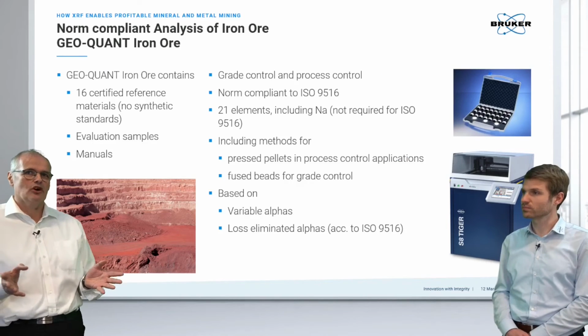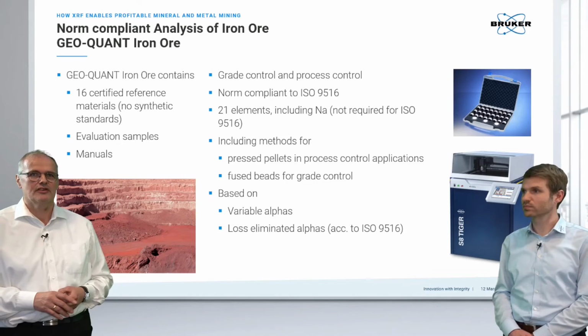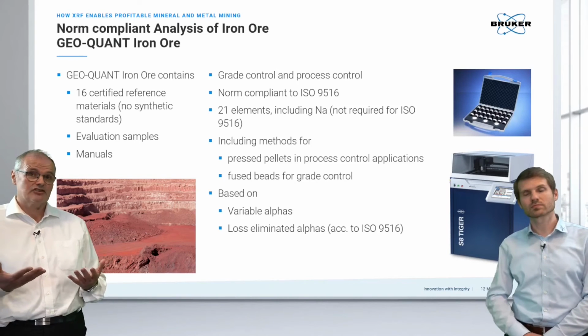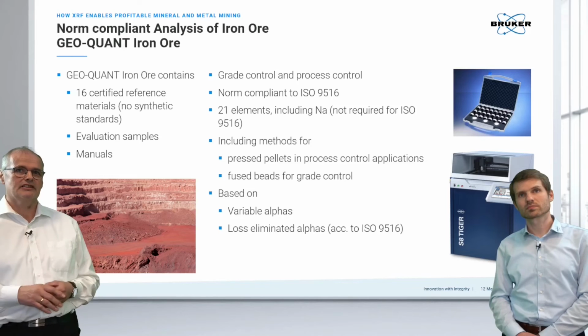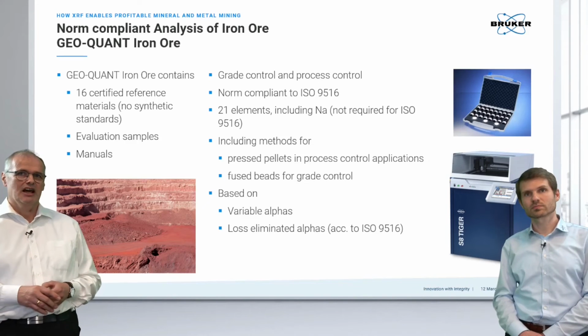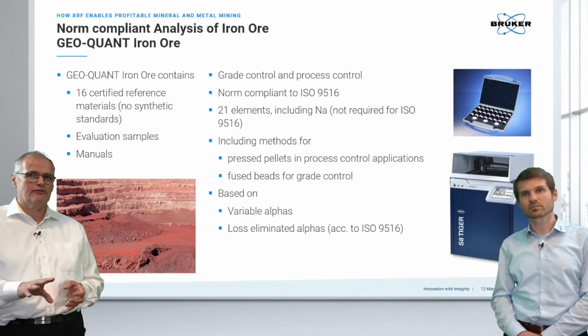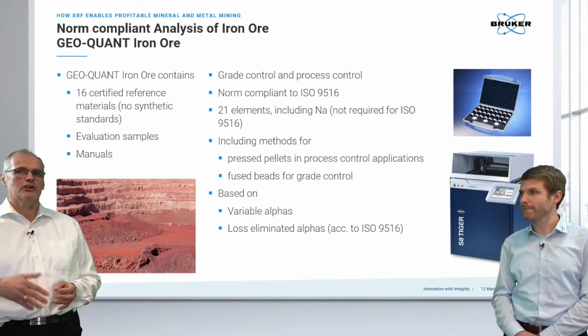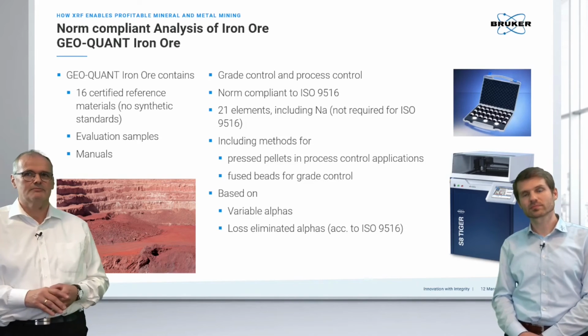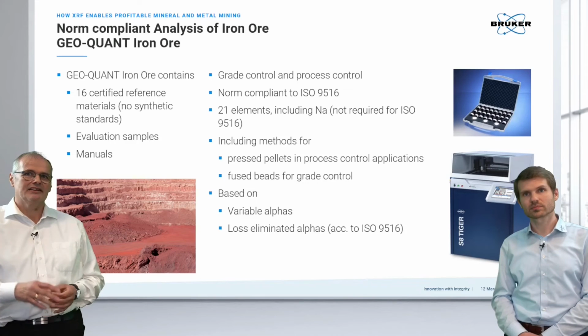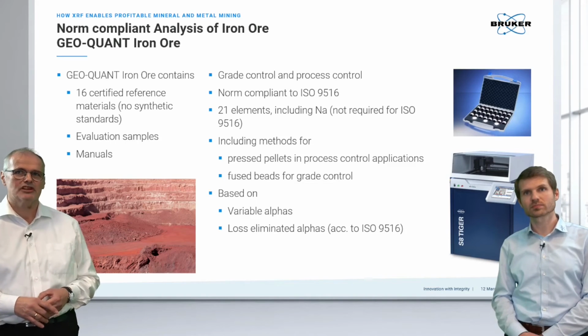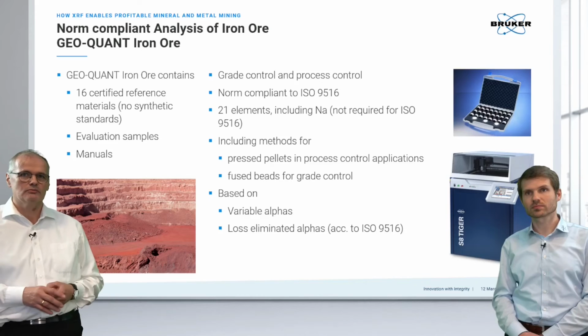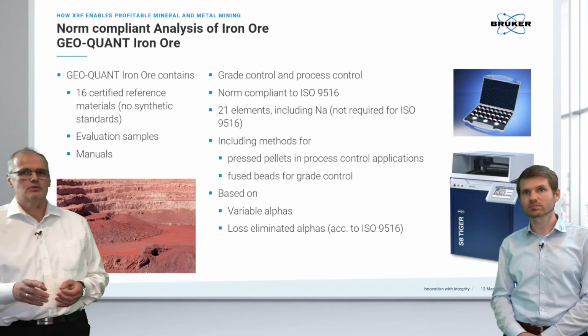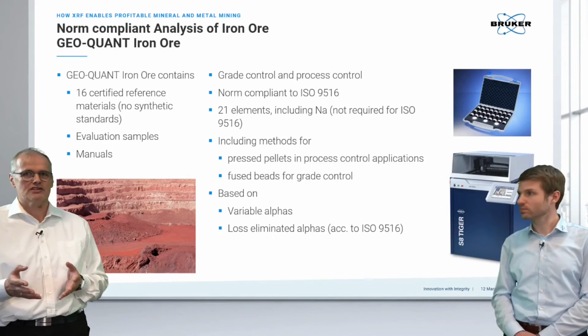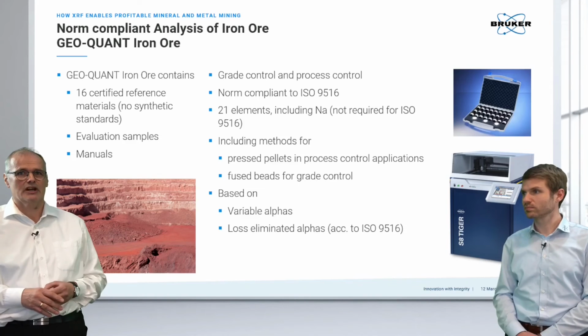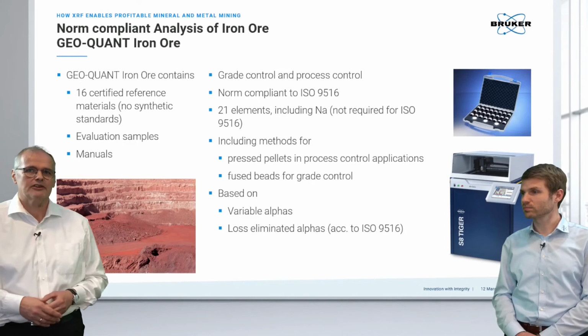So the GeoQuant iron ore package contains 16 certified reference materials, evaluation samples where we can check the quality, check samples and manuals. And this enables on the one hand the grade control following ISO 9516, but also the process control. So there's also a pressed powder method available. And it covers the 21 elements which are described in the norm, including sodium. And the nice trick here is we are working with pressed powder pellets for process control or fused beads in grade control. And we have two matrix correction models.